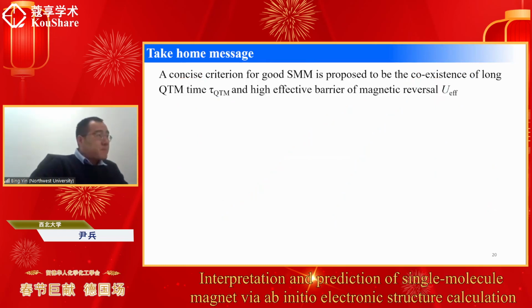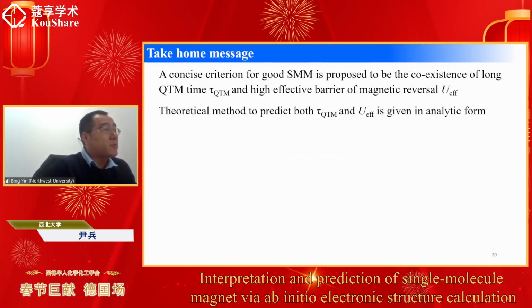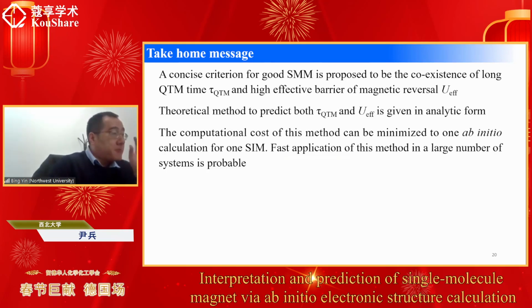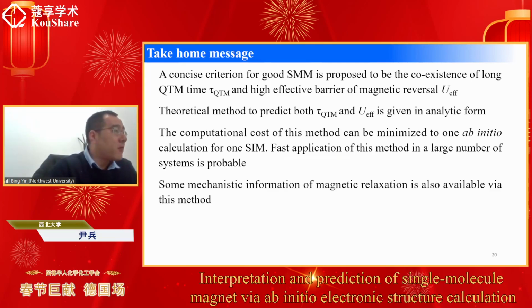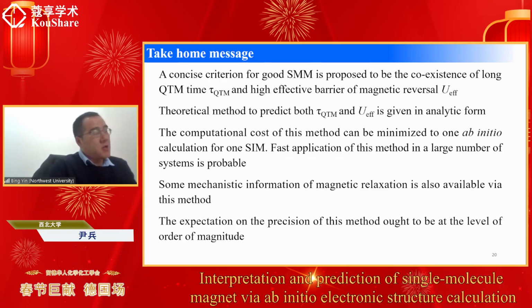Okay, there are some take-home messages. So we propose a concise criterion for a good single molecular magnet, and that is the coexistence of long QTM time and a high effective barrier of magnetic reversal, and we give a theoretical method to predict both of these parameters in analytical form. So the computational cost of this method can be minimized to one ab initio calculation for one single magnetic system. Fast application of the method to a large number of systems is possible. We can also provide some mechanistic information on the magnetic relaxation, but we also need to admit that the precision of this method is limited and maybe only gives the right order of magnitude.